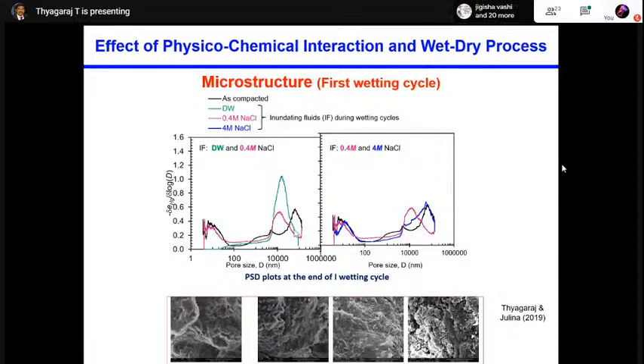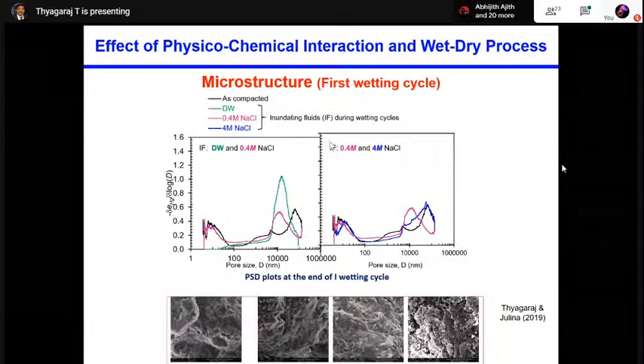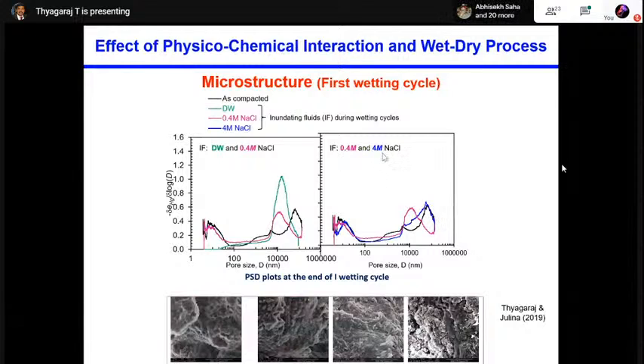You can clearly see from this figure that with the distilled water, the macro pore size is here, but with 0.4 molar, it has reduced. This is during the first wetting cycle. But when you compare 0.4 molar and 4 molar, you can see clearly the macro pore size increased for the case of 4 molar. Because of the suppression of the diffuse double layer, the macro pore size is increased. Whatever we discussed earlier, macro pore size has increased.